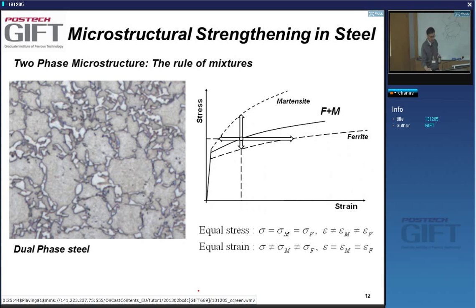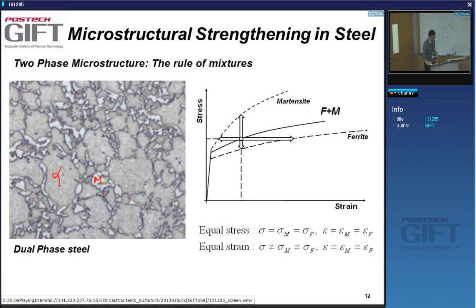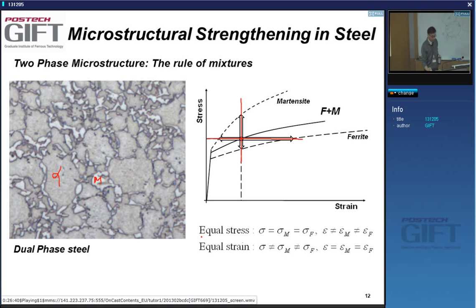Let's have a look at the DP steel. I have ferrite, and then martensite — these white islands are martensite. So I have a soft phase and an extremely hard phase. Schematically: ferrite here, martensite here. From composite theory, there are two extreme cases of stress and strain partitioning: you can assume the stress is the same in both phases — equal stress — or that the strains are the same in both phases — equal strain. In practice, the situation is somewhere in between.